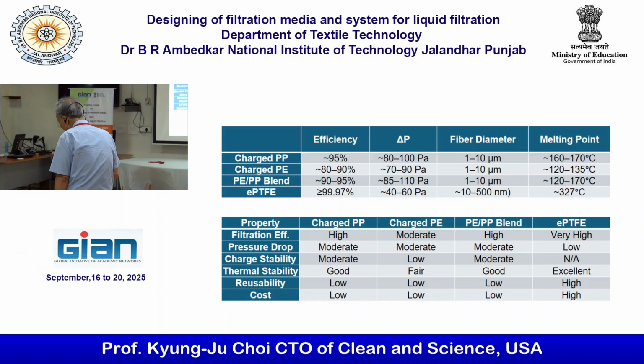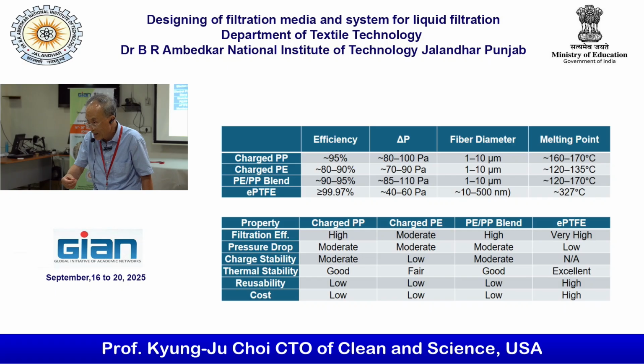Here, the electrospun material, the key issue is strength. So, electrospun material, you can use it in the air, but if you want to use it in the liquid, then it has to bond with a certain material, really highly bonded certain material. You know why? Strength of individual fiber is really low. So once you rub it, it just becomes powder. Even if you are rubbing slightly like this. That's why the electrospun fiber is tough to use in the liquid area. Yeah, I believe that they can use.